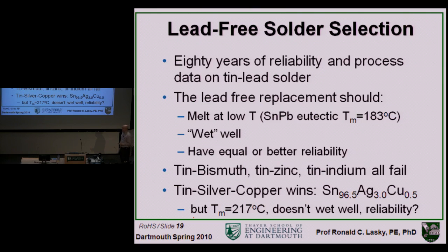Hundreds of millions of dollars were spent. People studied tin bismuth solders. You can get tin bismuth solders that melt at a low temperature. Tin zinc melts at a low temperature. Tin indium melts at a low temperature. And one of the issues with using tin indium is the amount of indium produced in the world is 1/5 the amount of gold produced in the world each year. And most of it goes in the material for your flat panel displays. Without indium tin oxide, at least in this state of technology, we would essentially not have flat panel displays. So there isn't enough indium to make solder for electronics. So the winner was tin, silver, copper. And I'm making a long story very brief. The one that's kind of settled down is close to eutectic.